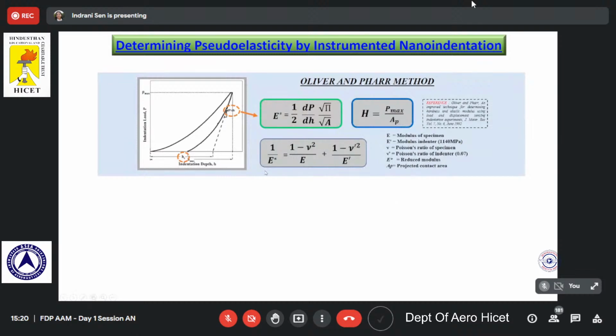From this kind of P-h curve, the indentation load versus indentation depth curve, we can do a lot of studies. We can find out the elastic modulus of the sample. We can find out the hardness of the material. We have done all these things.